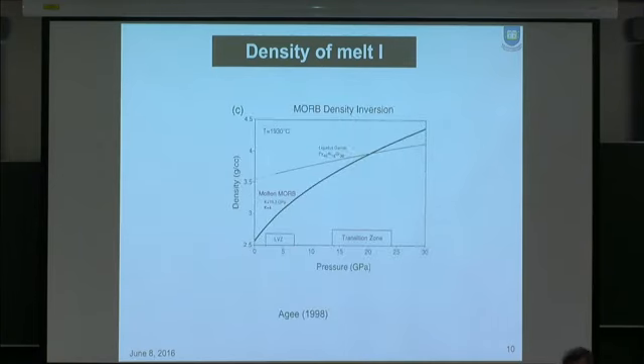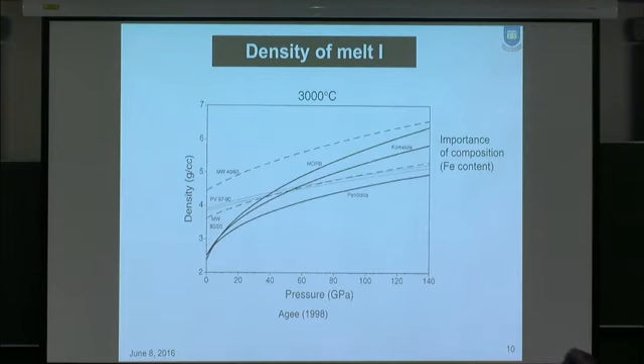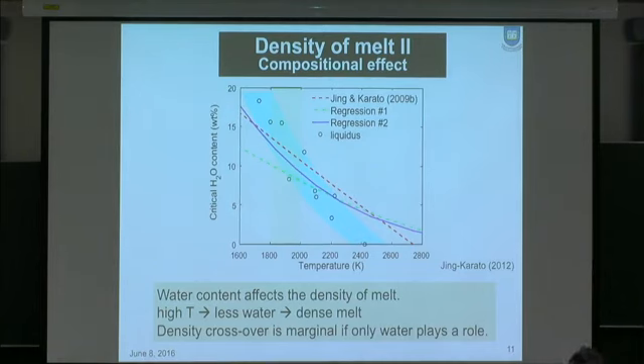There are some experimental tests for the Stolper hypothesis done by Carl Agee a long time ago, followed up by Agee and Otani, largely confirming the prediction of Stolper that melt density goes up with pressure much faster than solid density, and therefore at a certain point there's a possibility of density crossover. Of course, this also depends on the composition, which, as I mentioned to you earlier, for instance, if melt is iron-rich, density tends to be much higher than iron-poor melt. And there are some complexities in terms of the influence of composition.